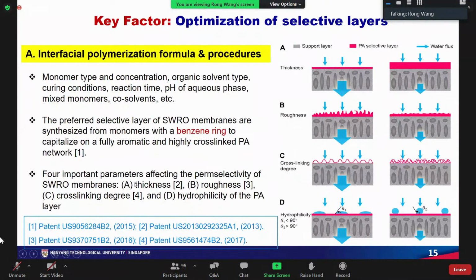We understand that for the TFC-RO membrane, the selective layer plays a critical role in determining the membrane performance. So a lot of the R&D focuses on the optimization of the selective layer. We can change the interfacial polymerization formula or procedures in order to adjust the matrix structure and finally fine-tune the membrane performance. Four important parameters will affect the selectivity of SWRO membranes, including thickness, roughness, cross-linking degree, and the hydrophilicity of the polyamide layer. So by changing the interfacial polymerization formula and the procedures, we can change these parameters.